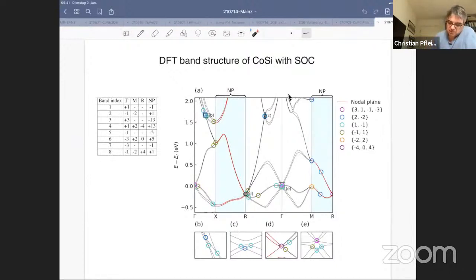And then the nodal planes, which correspond with the Brillouin zone boundaries, are shown here in light blue shading. And then you get these different crossings all over the place. So they basically categorized them, looked at the windings with different methods, calculated the Berry curvatures and so forth, and mapped them out for these different bands. Right? So you can see that there are these degeneracies on the nodal planes. You can always see these bands going together, and then you have these crossing points in these different locations.